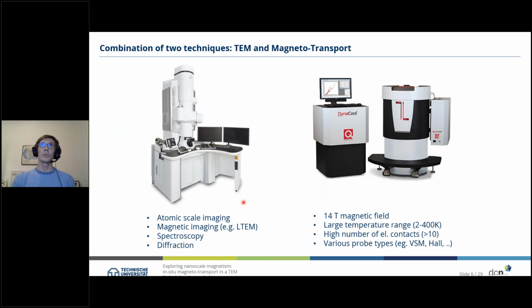two techniques. On the one hand side, transmission electron microscopy, as you might all know, and on the other hand, a magneto-transport setup. Of course, the TEM has the power of going up to atomic scale imaging. We can use very high resolution magnetic imaging using, for example, Lorentz TEM. We can do spectroscopy to analyze our sample to see if we have some segregation of different elements, to analyze the composition of our sample. We can do diffraction, which is very important to see how the grain orientation is, or if we reach the right crystal structure of our material.